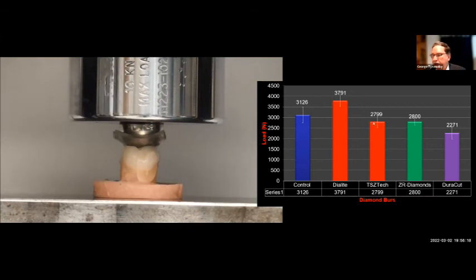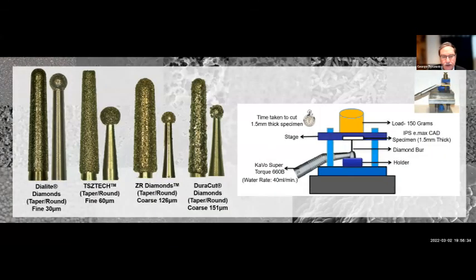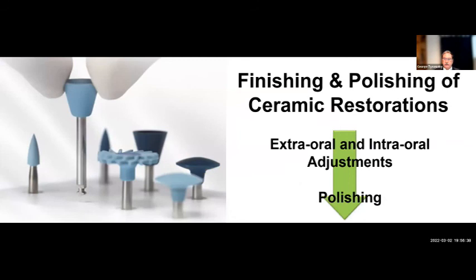And then you can see consecutively the degradation when we used coarser diamonds for creating these access holes, accordingly for the access preparations for these areas. So again, fine diamonds and copious water spray is the best situation in adjusting and also penetrating some of these restorations. I'm gonna jump through this.